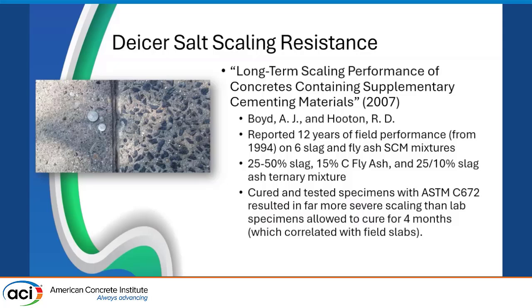Then we get into a couple of papers on de-icer salt scaling resistance. There's sometimes been a knock on slag or even fly ash for de-icer salt scaling, being on the commercial side of going into new markets, where they don't finish it correctly. They trowel in the bleed water, and then you get salt scaling. What this actually showed, in a controlled environment, was a report on 12 years of field performance on 6 slag and fly ash SCM mixtures: between 25 and 50% slag, 15% fly ash, and a ternary mixture. It looked at cured and tested specimens with ASTM C672 and found this was a very, very severe test compared to when you allow the slag to cure for about 4 months and then put it through the testing regimen.